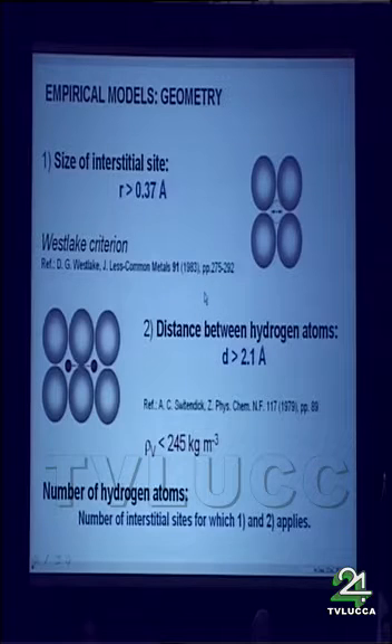Now we have several rather simple models to estimate, or to calculate, the amount of hydrogen we could absorb in a metal. There are certain criteria which have to be fulfilled. One is that the interstitial site has to have a certain size, otherwise it is not occupied with hydrogen, and the radius has to be greater than 0.37 angstroms. Then a second criterion is that the distance between two occupied sites with hydrogen has to be at least 2.1 angstrom. I will show you examples where this is not the case.